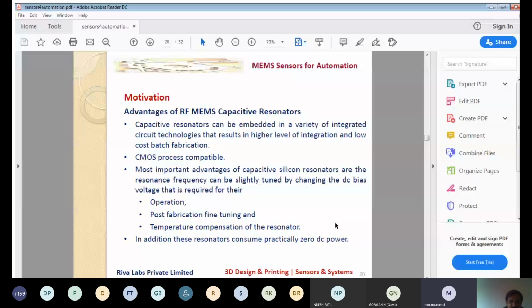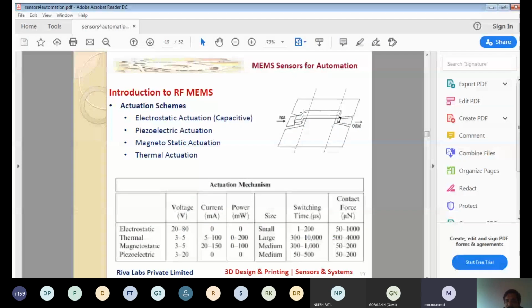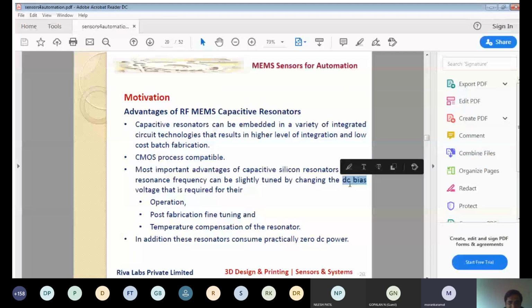What all these three mean is, let us say I want to fabricate this upper electrode and my dimensions are 10 micron by 100 micron. But when I fabricate this, it is fabricated as 9.5 micron and 99 micron. I wanted to make it 10 micron, but it became 9.5 micron, and I wanted 100 micrometer, but it became 99 micrometer. I wanted to apply, let us say, 5 volt. Now it has reduced to, let us say, 4.9 volt, because the dimensions of the upper electrode have reduced because of fabrication issues. So the 5 volt which is required to pull this down is now reduced to 4.9 volts, and this DC bias has to be reduced to 4.9 volt. Therefore, post-fabrication fine tuning is possible using this capacitive silicon, that is, the electrostatic activation mechanism.